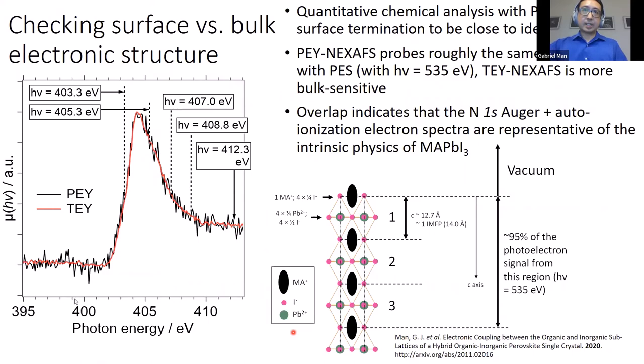As an additional check, we can do partial electron yield, which is sort of like Auger electron yield, and total electron yield NEXAFS. The plot on the left shows two measurements performed simultaneously. PEY was done using the RTOF spectrometer with a 50 eV kinetic energy cutoff, and TEY was recorded by measuring the sample drain current. And they both overlap on top of each other. That's a pretty good sign that the sample, both in the surface region and in the more bulk region, is basically the same. The reason this is important is because the Auger or Auger-like nitrogen KVV electrons are coming out with kinetic energies of roughly 350 eV or so, so they're really coming out from the top 2-3 unit cells. So it's important to make sure that the surface electronic structure is comparable to the bulk electronic structure.